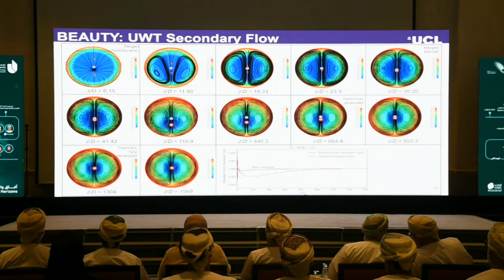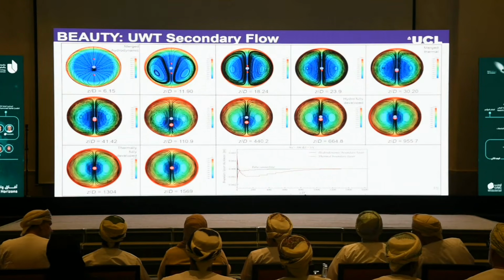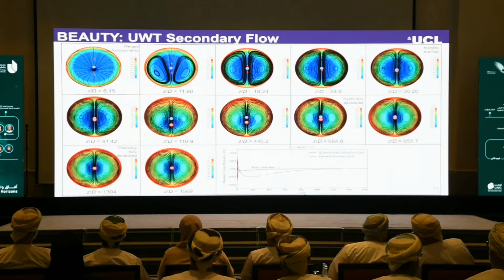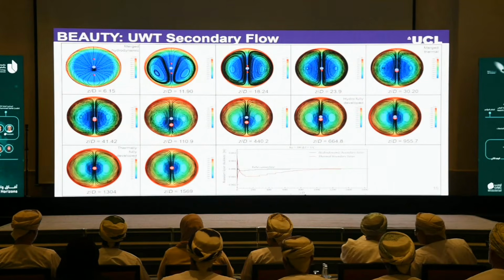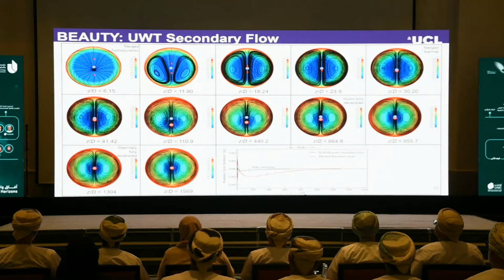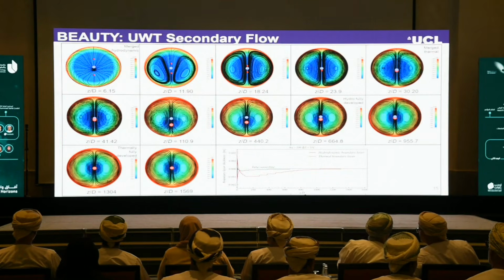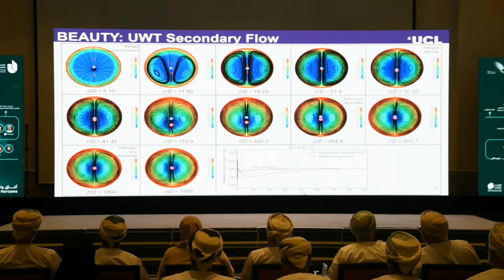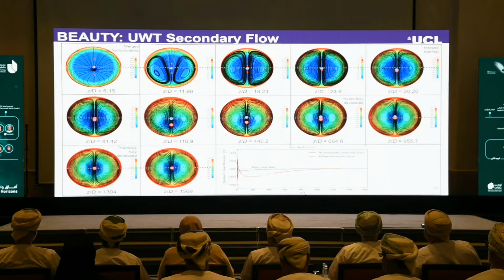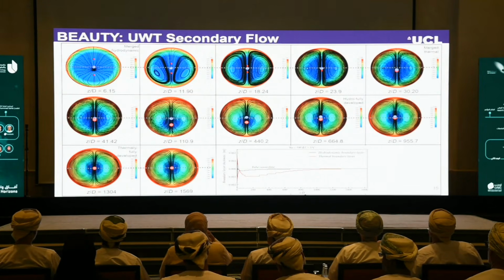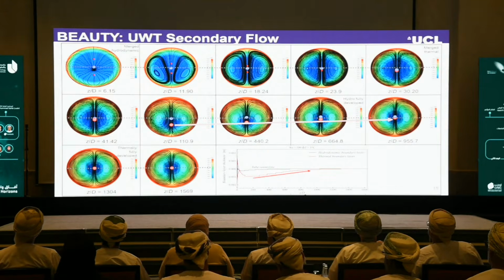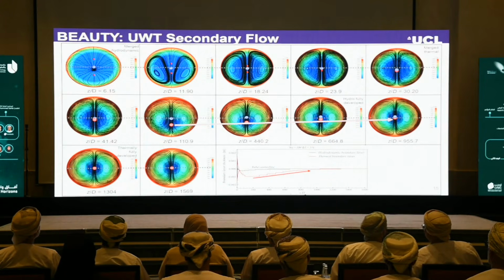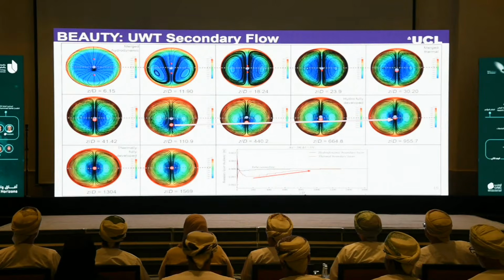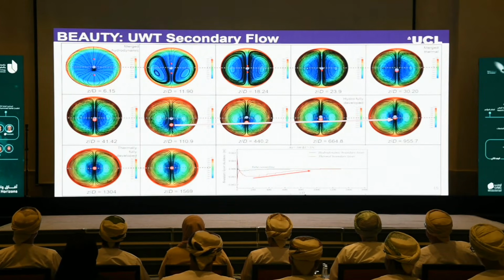So similar to the previous one, I've had a look at the streamlines and the temperature profiles inside the tubes, and it looks more or less the same. However, you would see that now the streamlines are much more symmetrical, which is good, but it's also not that good because it tells us that mixed convective behavior is quite suppressed in this case. And again, dotted lines just for reference where the center line is. We can see that this merging point, although it developed quite below the center line due to mixed convective effects, as the flow further developed, it moved back and very much to the center line.